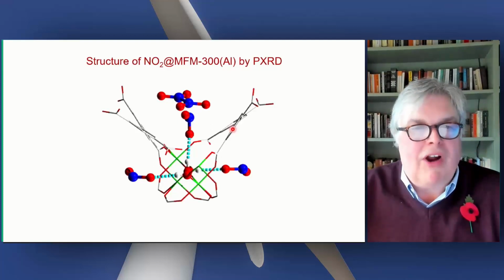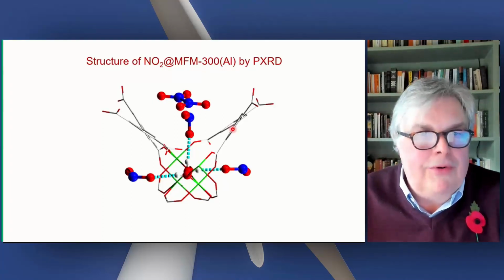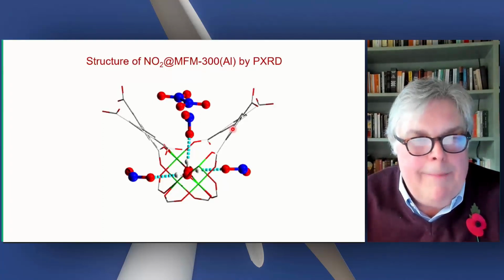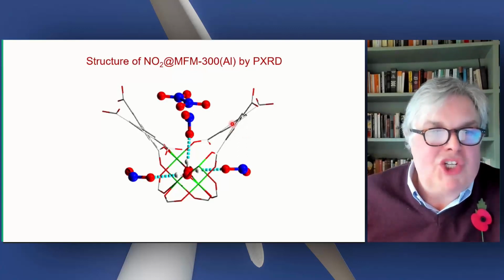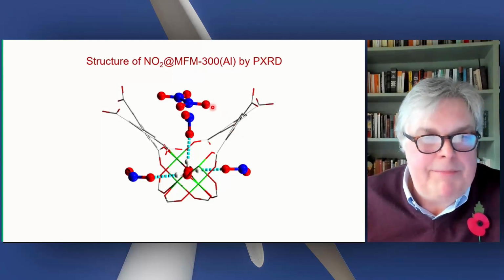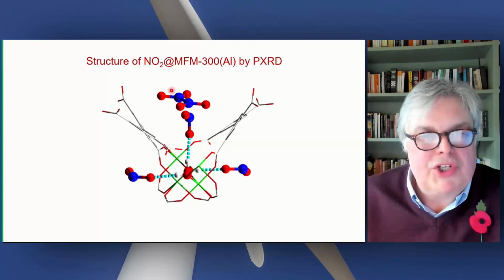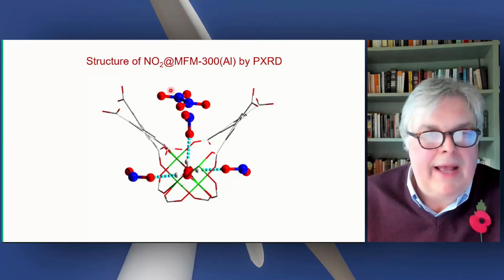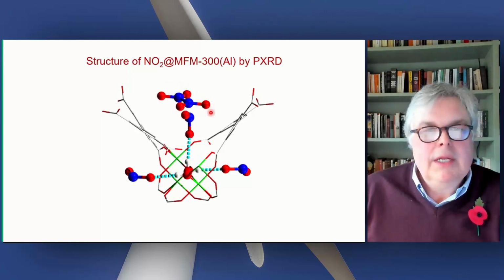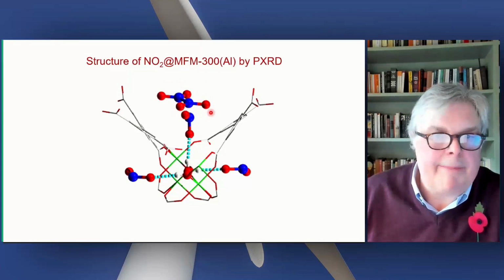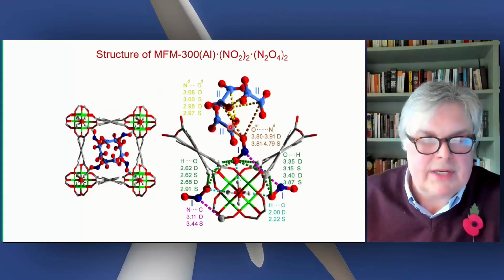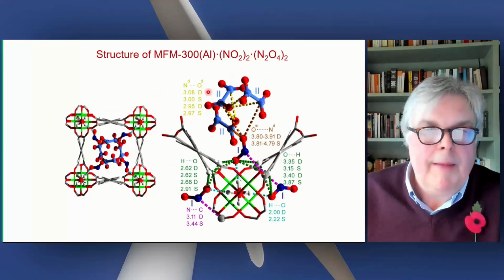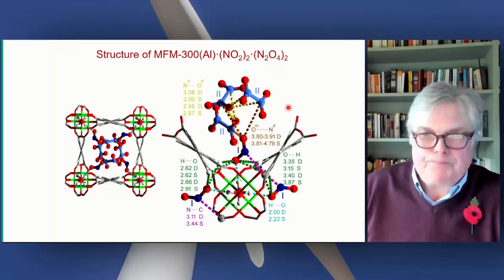This hides a whole variety of sins. If you look at NO2 within this MOF, you have an NO2 to N2O4 dimerization, I think as many people know. So therefore, depending upon the temperature, you see different proportions of NO2 and N2O4. And I just illustrate this. Here is NO2 interacting with the OH group, and there's N2O4 within the pore. So this is a very complicated structure. It's temperature dependent because of the dimerization or dissociation of the NO2 within the pore. But we got there in the end with a static structure here with this stoichiometry.